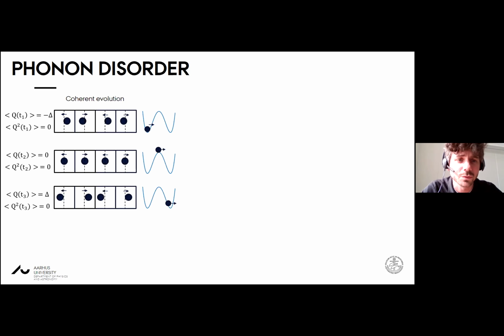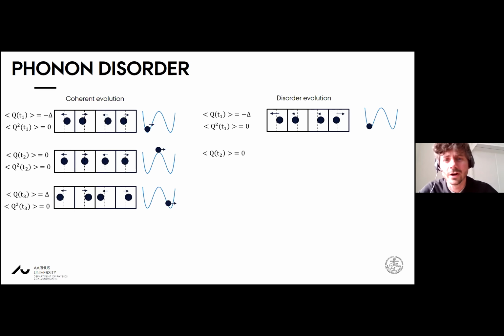And so then we would switch from one phase, one twin, as we would call it, to the other twin in a coherent fashion. That cannot happen in the disordered evolution. So in the disordered evolution, the forces can no longer be uniform on each atom. So each atom cannot just move along the high symmetry direction, but it has to move in a random way.